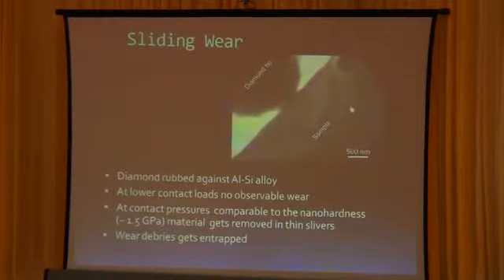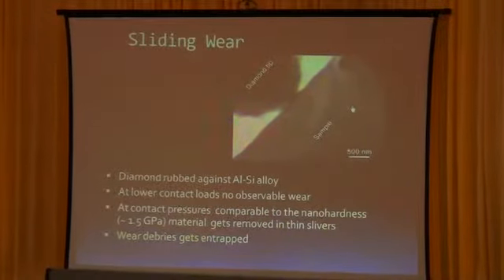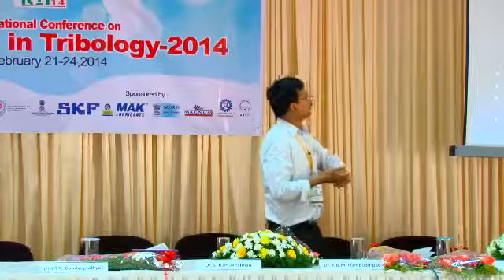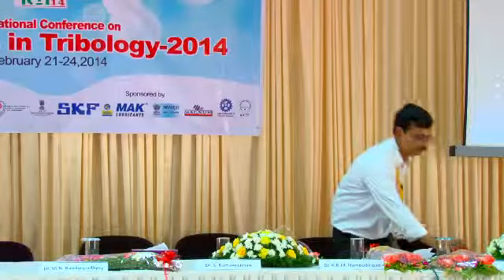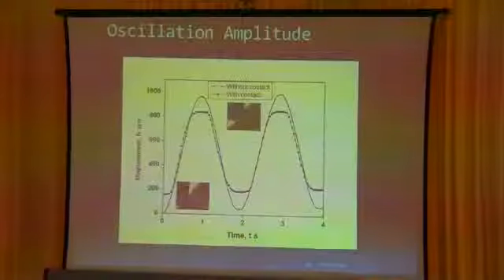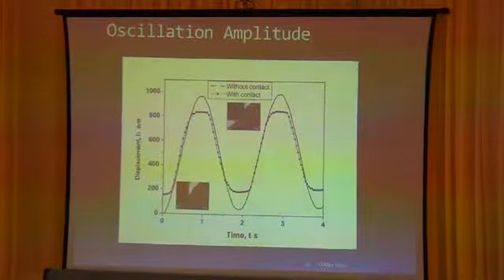So at very low load, at the very low contact pressures which we have estimated, no material gets removed. At about 1.5 GPa, we can see material being removed layer by layer, and that gets accumulated on the end of this. Okay. What we can also do is measure how the amplitude of oscillation is changing. I am taking a pen like this and moving it. I know how much I am moving, but this end is not moving by the same amount. It is moving less because of friction,